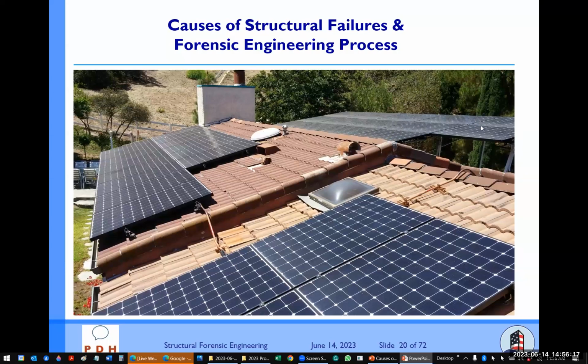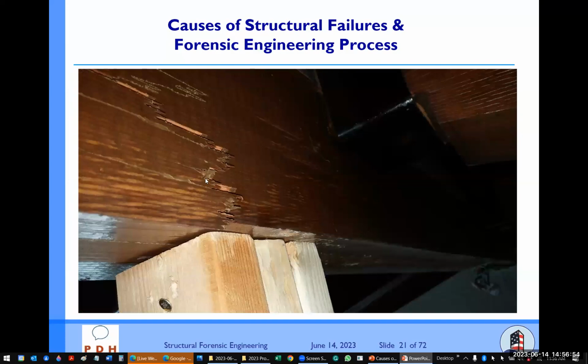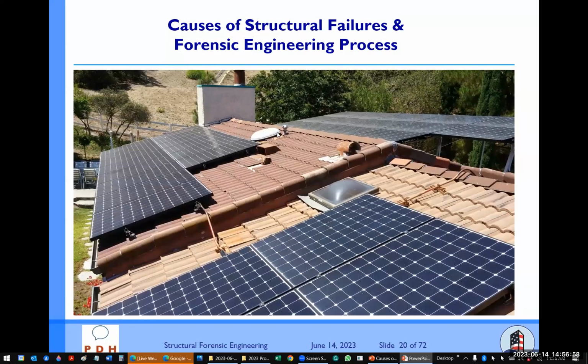They're elevated way above. So this roof slopes toward the left, and that part from this ridge slopes toward the right and is going down. Then the contractor decided to elevate them on like 6-foot vertical posts. And then you can figure out the problem: concentrated load going into the members, and also the wind uplift and all kinds of stuff. So it caused the fracture of this ridge beam. This ridge beam is exactly under here, and they were not accounting for the complications. So I required immediate temporary shoring, which they put here on the bottom.